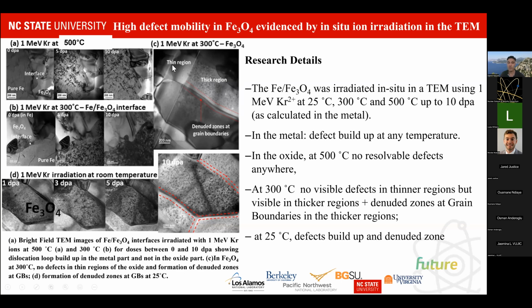And you have a clear illustration here, where you have the same grains, the very large grains of oxides, but with 2 different thicknesses. This is managed by the FIB process, the sample prep process. We can control the thickness of the different regions in the sample by FIBing more or less those regions. And you can see here clearly that in the thick part of the same grains, you have accumulation of damage and growth of loops, and not in the thin region. When we are at room temperature, it doesn't matter where you are and the thickness. At that point, you see the formation of defects.